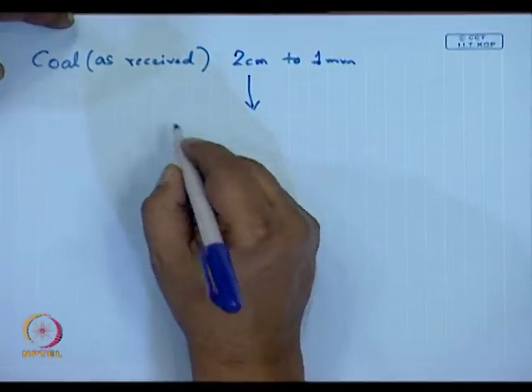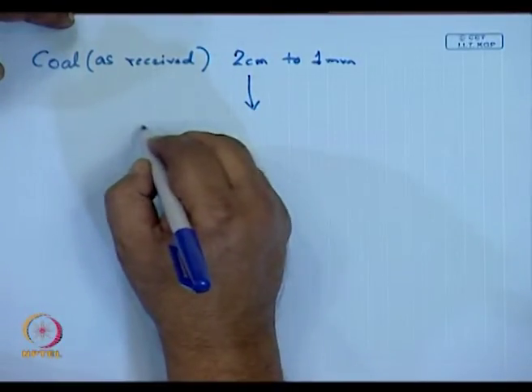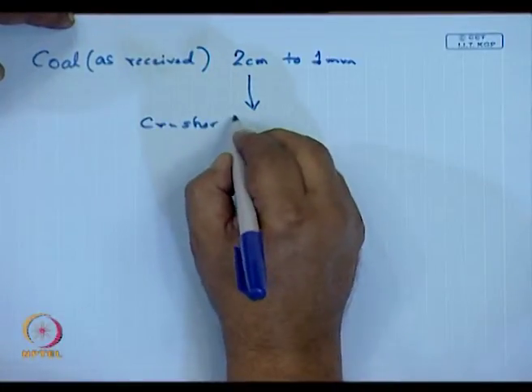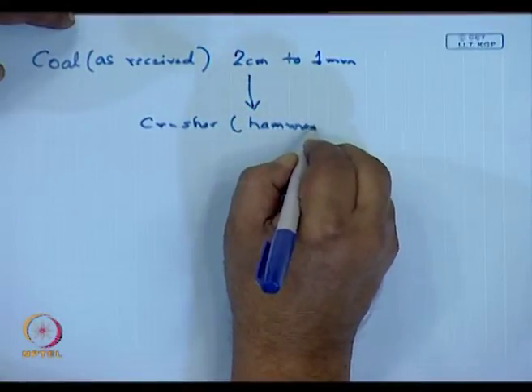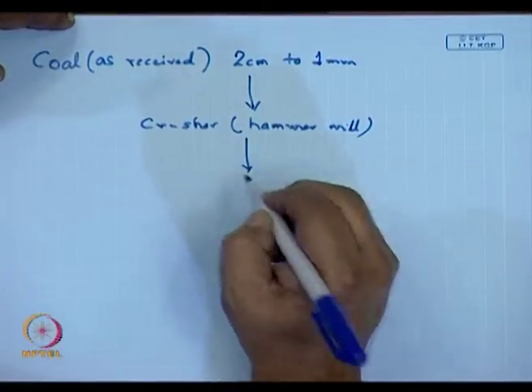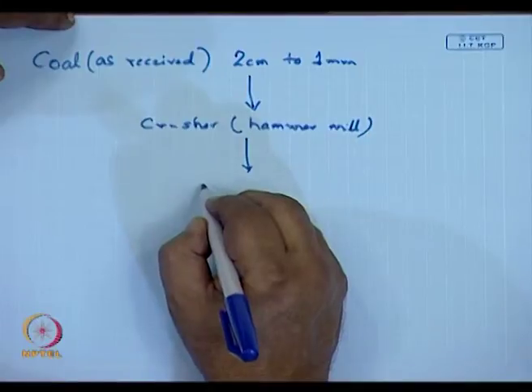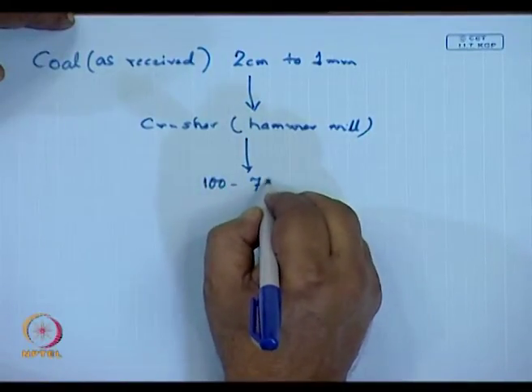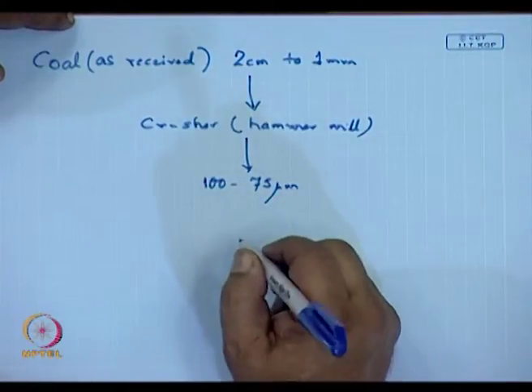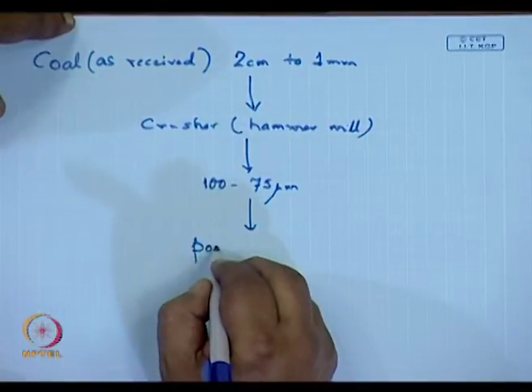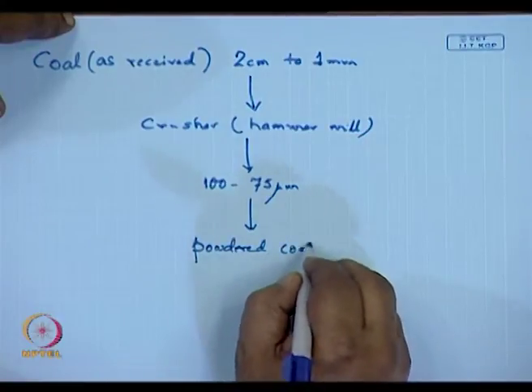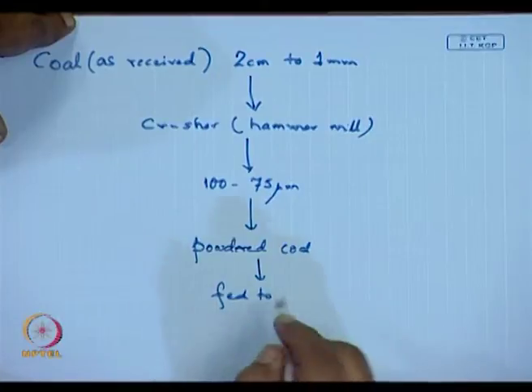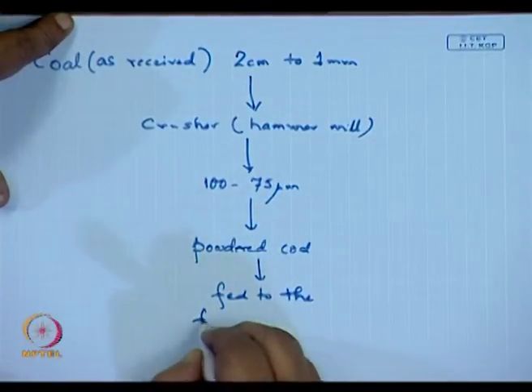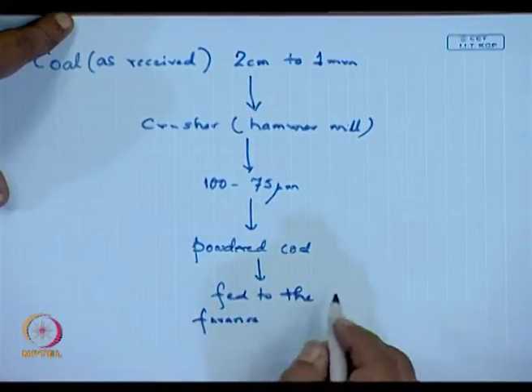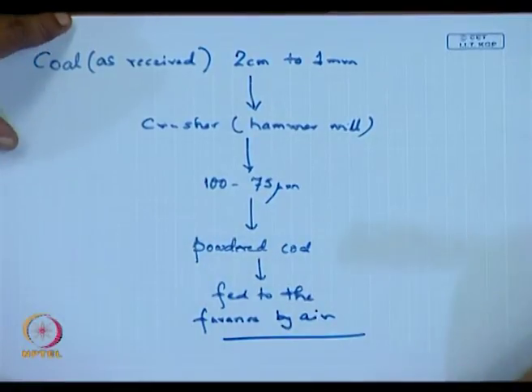is first taken to a crusher, which is normally a hammer mill, where the powder sizes are decreased to, say, 100 to 75 micrometers. I talked of hammer mill earlier, and this powdered coal is fed to the furnace by air. This has been a standard process for a very, very long time.